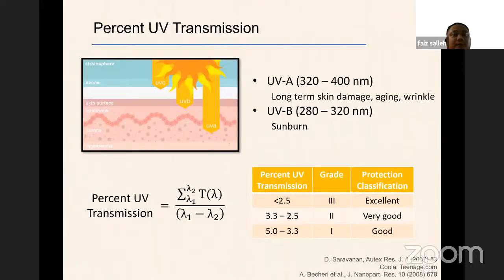And then, if we look at the ability to repel or block UV light, we also did a measurement in the UVA and UVB range, around 320 to 400 nanometer for UVA and 280 to 320 nanometer for UVB. We know that UVA and UVB can affect the biological body, especially UVB, and UVA can go deep inside our skin. So here we have calculated the percent UV transmission. It's reported that if we have less than 2.5% UV transmission, we get a grade 3, which is classified as excellent protection.